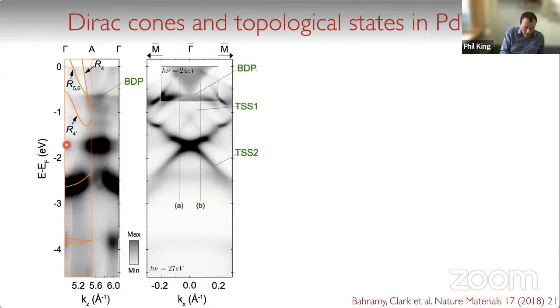Now, it turns out that in these band gaps, you can see actually some constant spectral weight, so spectral weight that doesn't vary as a function of the out-of-plane momentum. Now, it's very clear in this large band gap. It's a little bit more subtle in this small band gap. But if we look at the in-plane dispersion measurements of these, you can see rather similar features showing up. So if we start near to the Fermi level, well, not that near to the Fermi level, but a few hundred millivolts below the Fermi level, we see that where these states cross and form the bulk Dirac point in the system, we indeed have a Dirac-like feature coming out here. Now you see that this is very filled in, and that's due to the poor KZ resolution of photoemission. And so we have these 3D dispersive states that are forming this bulk Dirac point.